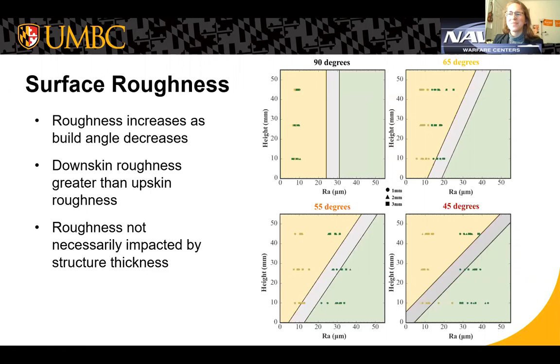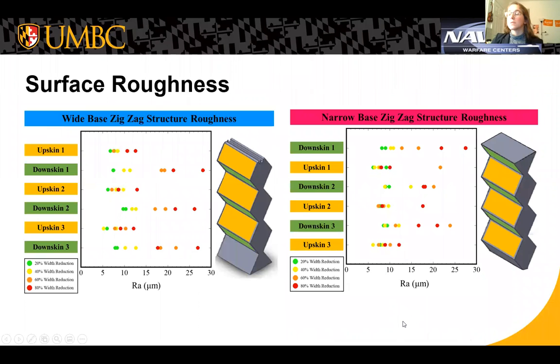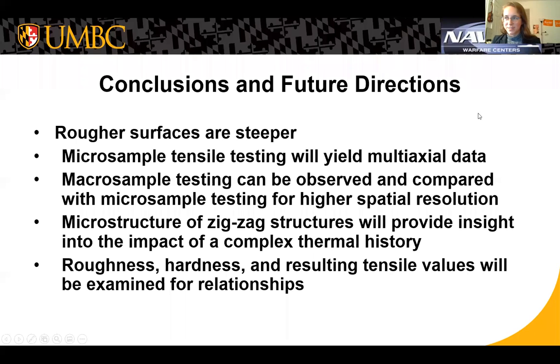We also realized that roughness is not necessarily impacted by the thickness of the structure build itself. This was further shown in the wide base and narrow base zigzag structure roughnesses. Now, the other interesting thing here is that height within the build doesn't really affect the roughness. We again see that steeper surfaces for the downskin have an increased roughness, but it doesn't really matter where the height is. It's still going to be around the same large value. So our conclusions: rougher surfaces are a lot steeper.